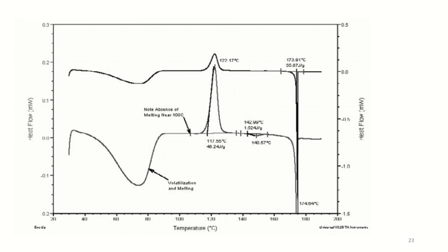This pinhole allows water to escape from the pan, which caused the conversion of the crystalline material into an amorphous form. The amorphous form crystallizes near 120 degrees Celsius and then melts near 174 degrees Celsius. In a sealed pan with water, which is about 5% present, the sample showed very little tendency to crystallize after it had melted.